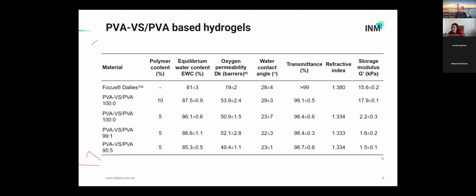Now we started preparing different hydrogels from PVA, and we came up with these compositions, just for you to have an idea of what kind of polymer we're dealing with. We're dealing with a mix of PVA and vinyl sulfone PVA with concentrations between 5 and 10%. Those concentrations give physical properties of relevance for a contact lens, which are close to the properties of the commercially available PVA-based contact lens in terms of water content, oxygen permeability, water contact angle, transparency, refractive index, and also storage modulus. So this is good because we are not far away from what is already applied, so we can fulfill the material properties, but still we know that under these compositions, they are also compatible with our cells.